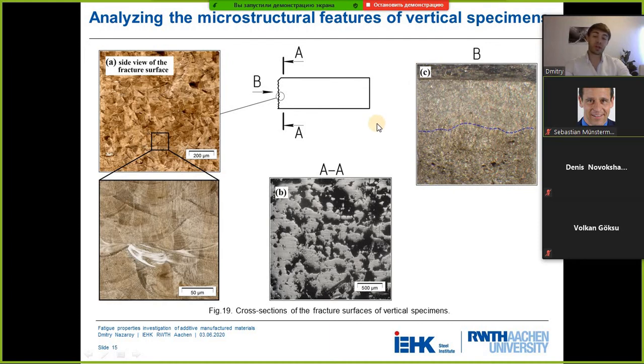Since the crack propagated coaxially, alongside the columnar grains, it propagated through the shorter routes, and that resulted in faster crack propagation. With regards to the porosity level, these specimens experienced a shorter time interval, lower temperature gradient, and therefore a slower cooling rate. Therefore, the material was a little bit overheated, and that resulted in a bigger diameter of the porosity. That triggered an additional crack propagation mechanism: jumping over cavities. So that facilitated the fast crack propagation.